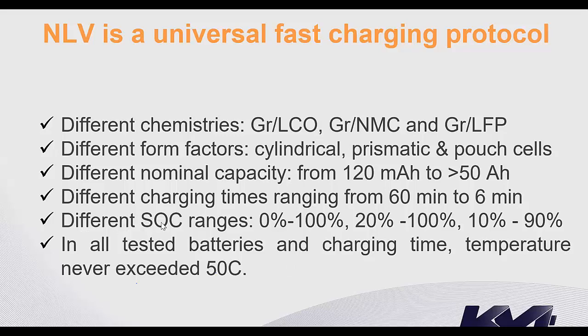And also the other thing is that we can apply NLV for charging from any initial and for any final state of charge, like from 0 to 100%, from 20 to 100%, from 10 to 90%. It depends actually on the application. In electric vehicles, the EV manufacturers will recommend the driver to charge their batteries when the state of charge falls to 20%. Don't wait to go to 0%. In some other applications like drills and cordless tools, it's recommended actually to go from 10 to 90%. So case by case, we can apply the NLV to different initial states of charge and final state of charge.